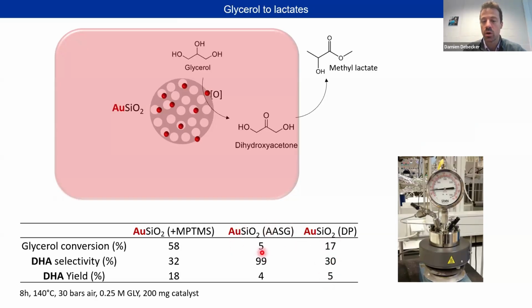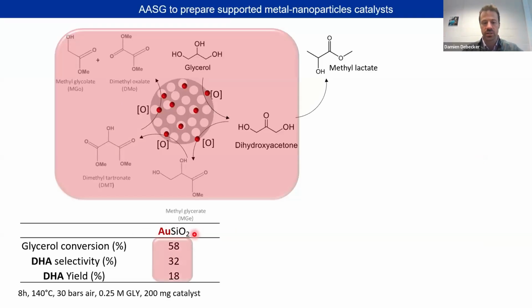For this one, where we try to put the gold directly, very poor conversion. Selectivity here does not really mean anything because conversion is so low, but you see here performance are very low. And for the one where we use this additive, that was more decent with these kind of values. So I will call this catalyst simply gold on silica, but you know that there is this mercapto group. You see here that we still have a challenge. Selectivity is only about 30%.